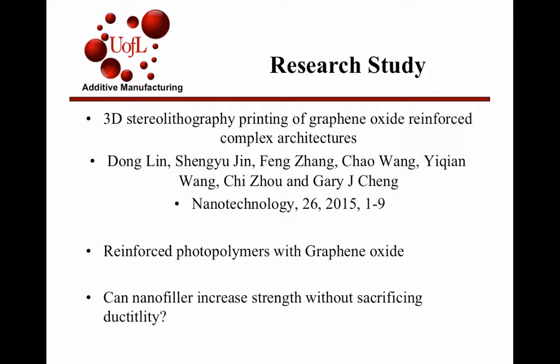embedded in the polymer. So the main question they wanted to ask was, can this nanofiller into this polymer increase the strength without sacrificing ductility? Because a lot of the studies previous to this had showed increases in strength, but the elongation had significantly decreased, the ductility was way down. So that's what they wanted to experiment with.